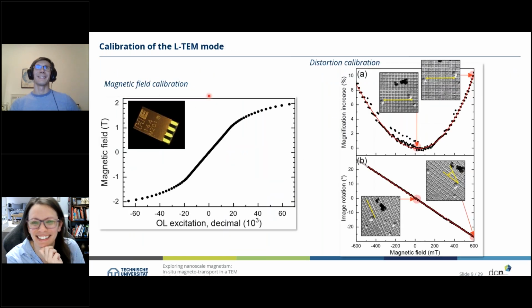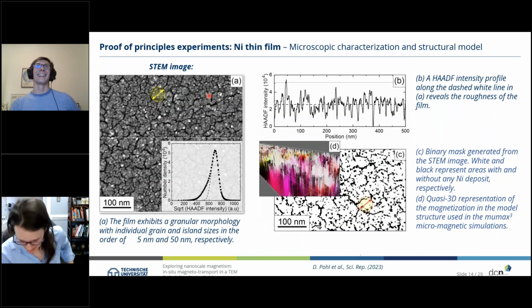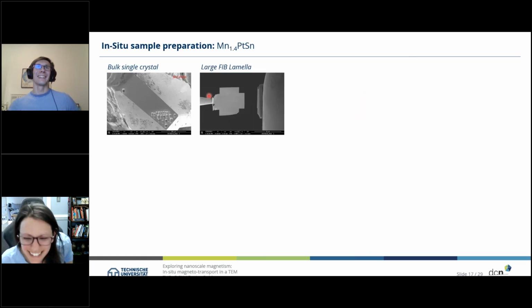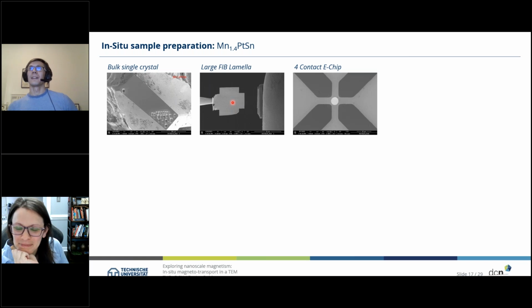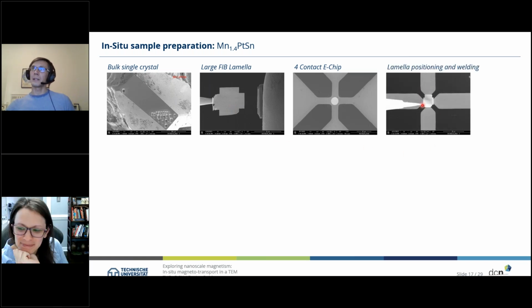There's always people interested in FIB deposition on chips. I mean, it's always tricky. Just look at the amount of lamellas which we prepared. So what we came up with is that it helps if you glue the needle not directly at the side but more on the top, so that you then nicely can place it down and then just rip it off the needle, not using the ion beam anymore. Just use the adhesion of the lamella onto the membrane and rip off the needle and then start to weld the sample on the lamella.